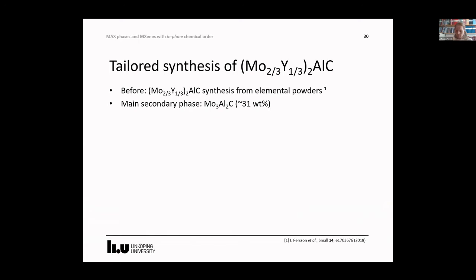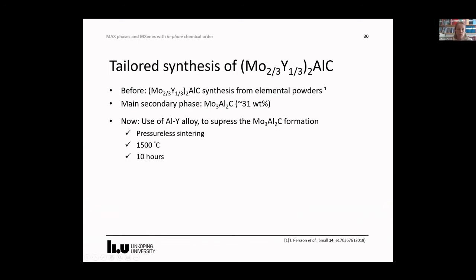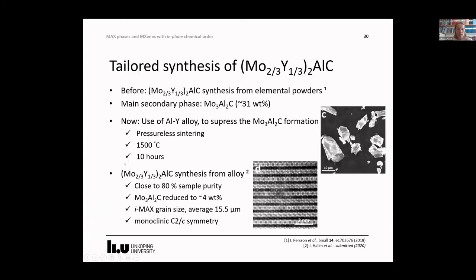So now, in a new project, we've tried to use an aluminium yttrium alloy to suppress this secondary phase formation. And what we got was IMAX synthesis with a close to 80% sample purity. This secondary phase was reduced to just about 4 weight%. We got nice IMAX grain size, average of about 15 microns. And zooming in, we find a high quality also on the nanoscale with a confirmed structure of monoclinic symmetry.